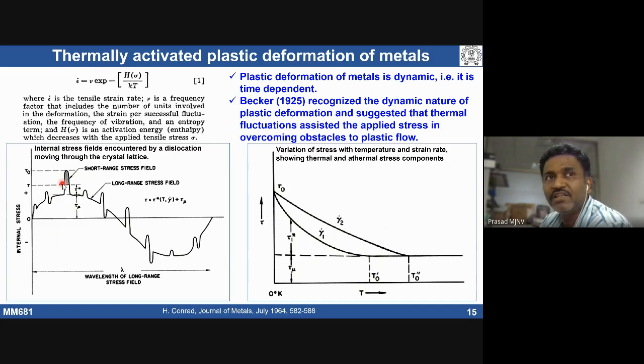I said an athermal barrier involves a long range stress field, which is related to at least 10 atomic diameters of size. The barrier will have a minimum of 10 atomic diameters or more. In the case of thermal barriers, the size of the barrier is less than 10 atomic diameters. So can anybody list down some athermal barriers and thermal barriers?